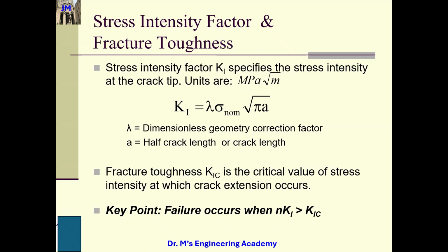So KIC is a material parameter. If you want to use a different KIC, you must use a different material, right? You cannot change it. It depends upon the material you are selecting. So, key point: this is a material parameter, and based on the loading condition sigma and geometry of this structure, you calculate the KI, and then you compare KI and KIC. If your KI is greater than KIC, that means the crack will propagate. If your KI is lower than KIC, that means the structure is safe under this loading condition.